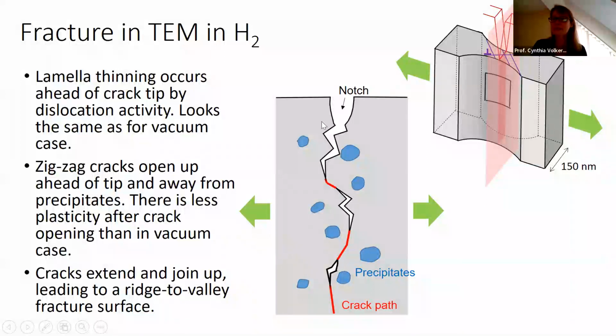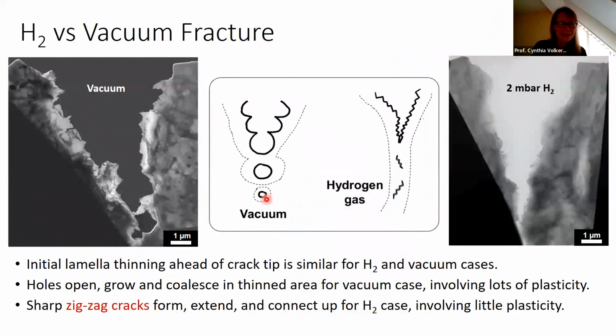Okay, so summarized now in this schematic, we first thin down ahead of the crack tip, as you see here on the upper right. Sorry, let me switch back to the laser pointer. And then the crack propagates by formation of these zigzag cracks on 100 facets ahead of the crack tip, and then these link up and lead to a ridge to valley fracture surface, which is very distinct from the ridge to ridge fracture surface that we have in the case of the vacuum. So summarized here, the difference between the two, these dashed lines are meant to indicate the thinned regions. So we see a very distinct difference in how these cracks form and in the resultant crack surfaces.